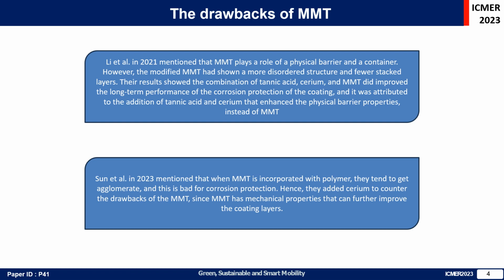As with many of the advantages of MMT, there are also some drawbacks of MMT. Li et al. in 2021 mentioned that MMT plays a role of a physical barrier and a container. However, the modified MMT had shown a more disordered structure and fewer stacked layers. The results showed the combination of tannic acid, cerium, and MMT did improve the long-term performance of the corrosion protection,